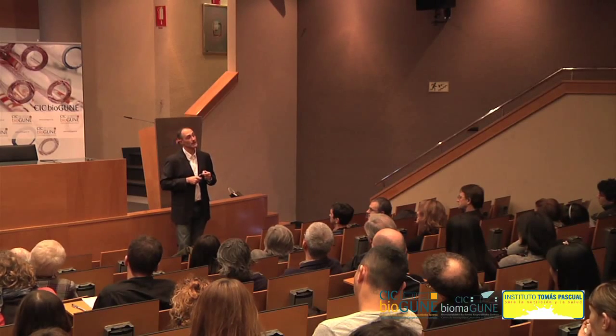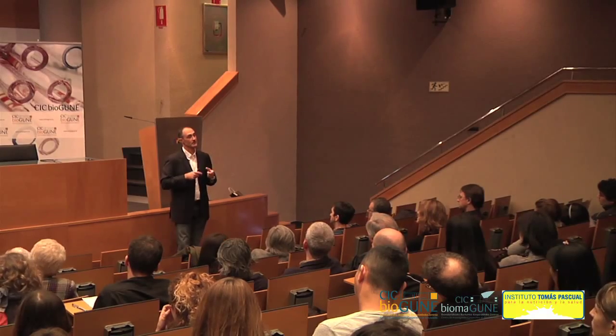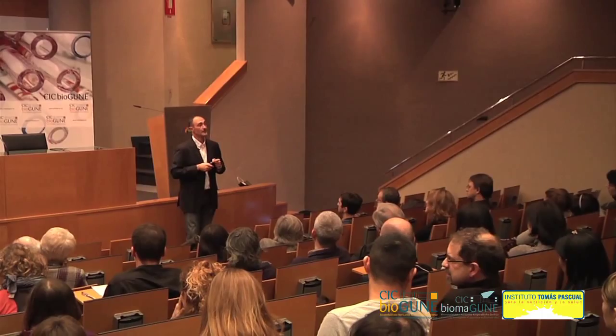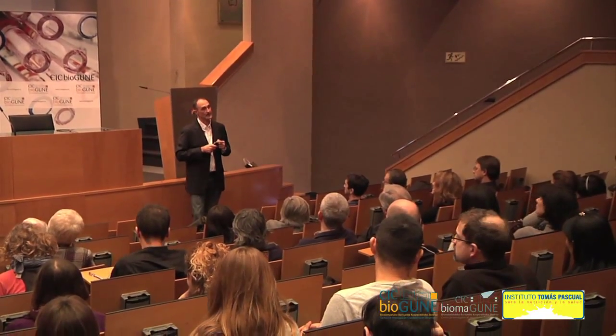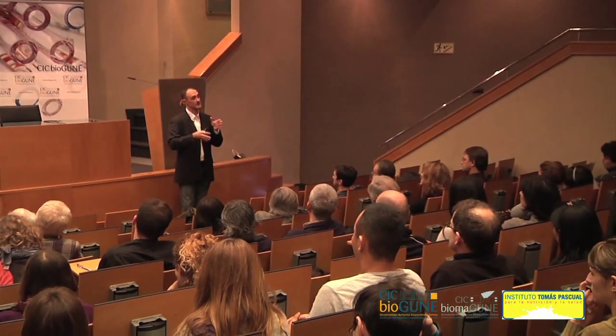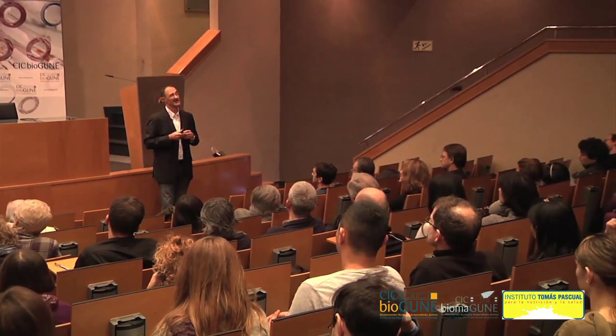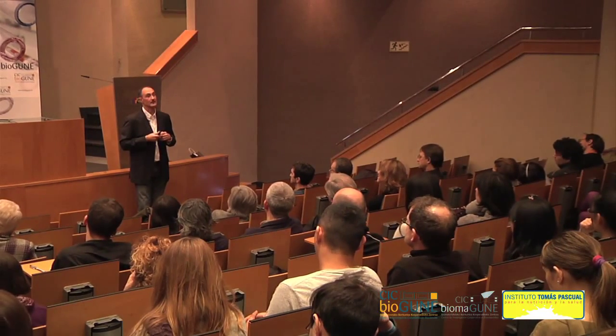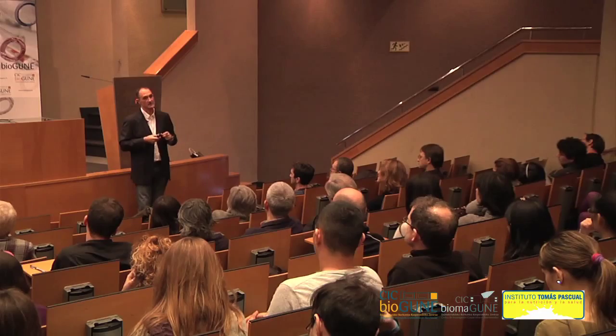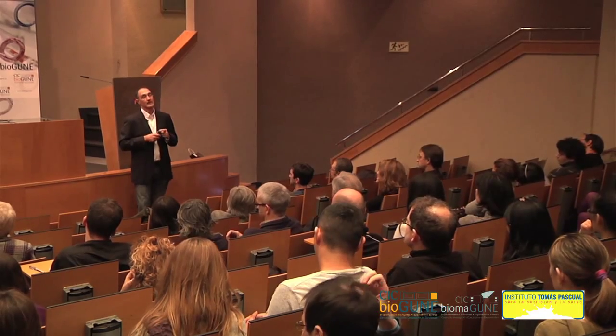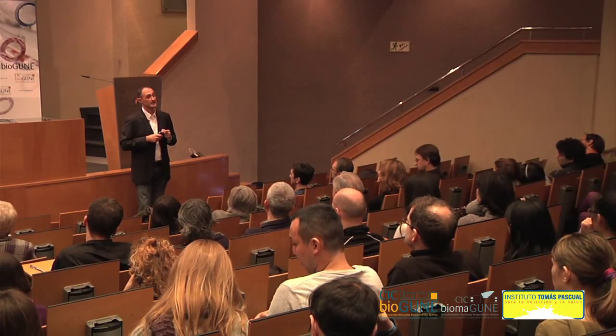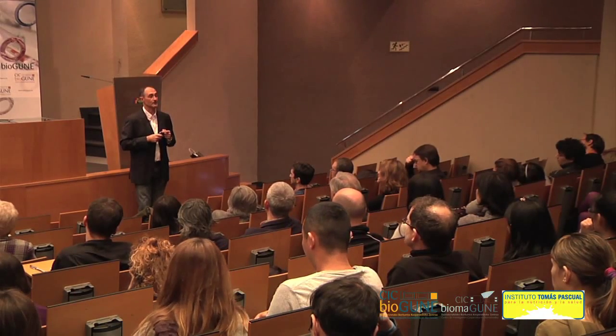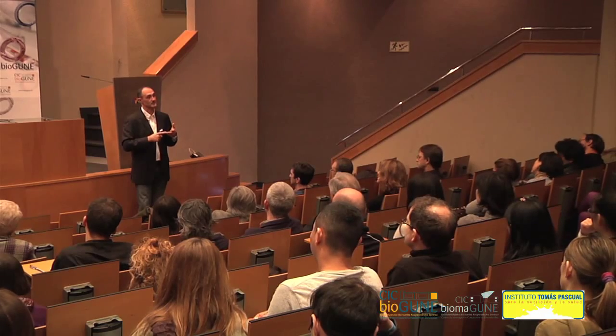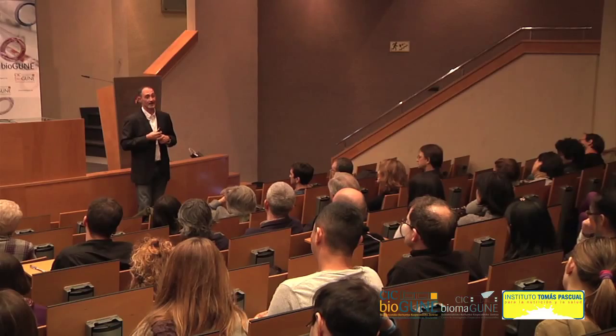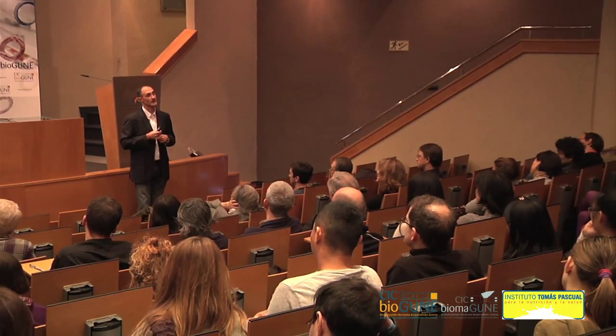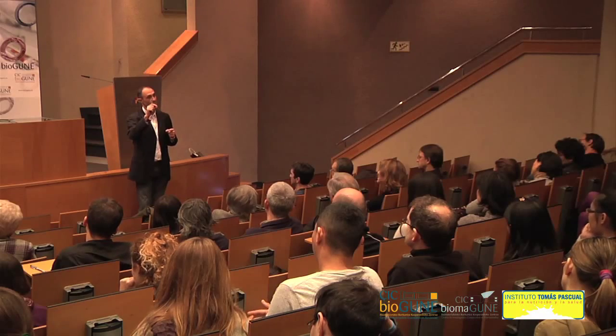How far you can do that depends a bit on which particles you're using and how deep you want to go. You can make the particles in such a way that they absorb near infrared light in the transparency window of tissue. I think that the reported deepest position is about 5 centimeters or something like that. How deep the particles go inside cells, this also depends again on many factors. It depends on the shape and the size of the particles, but also on the surface coating. I think that there is still a lot of work to do in that respect to really be able to direct the particles to specific locations inside the cell.